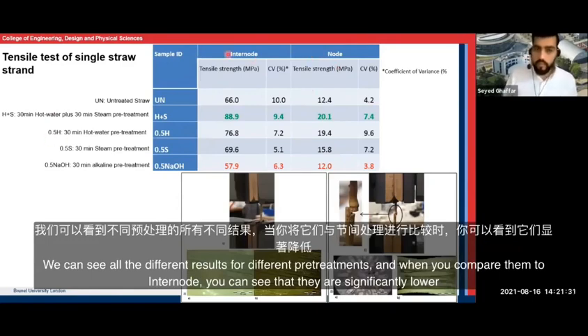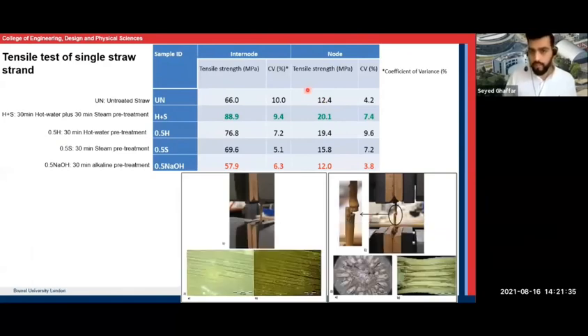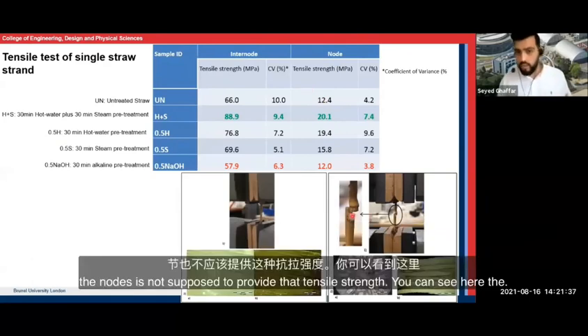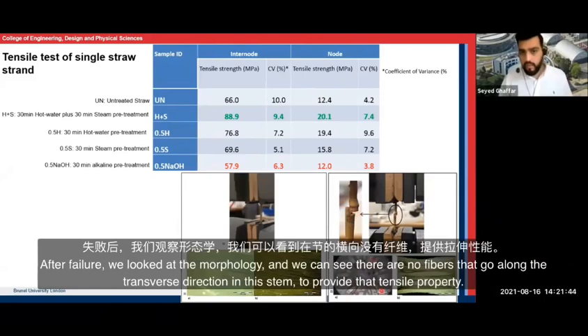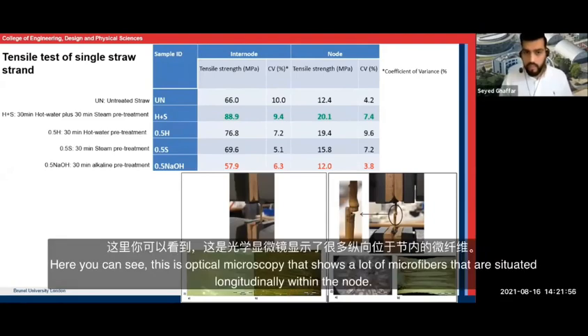And when you compare them to internode, you can see that they are significantly lower. And the node is not supposed to provide that tensile strength. You can see here that after failure, we looked at the morphology of the node, and we can see there are no fibers that go along the transverse direction in the stem to provide that tensile property. Here, this is an optical microscopy that shows a lot of microfibers that are situated longitudinally within the node.